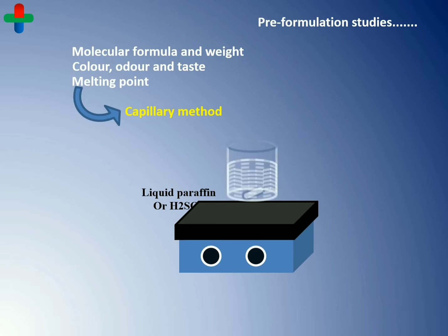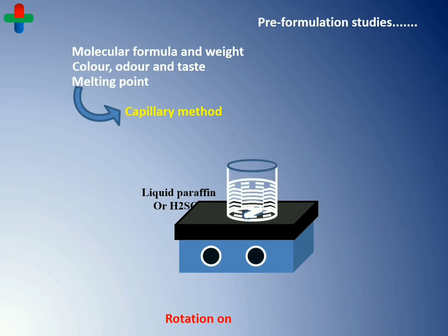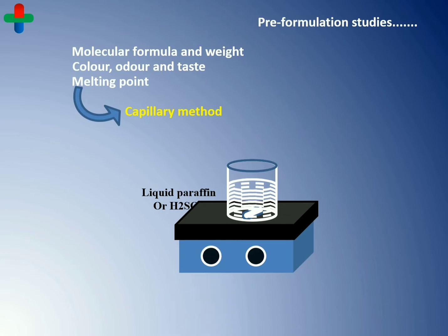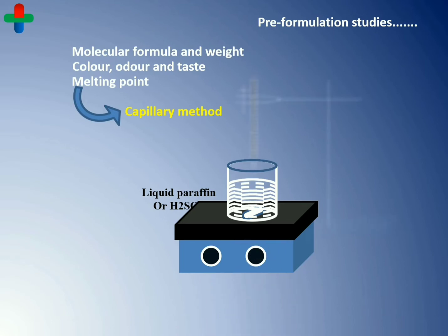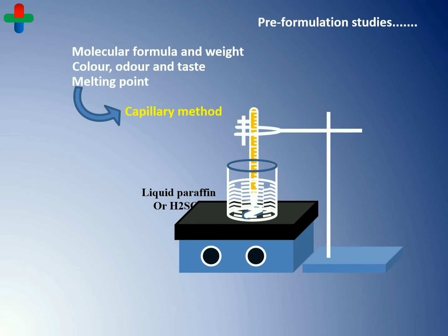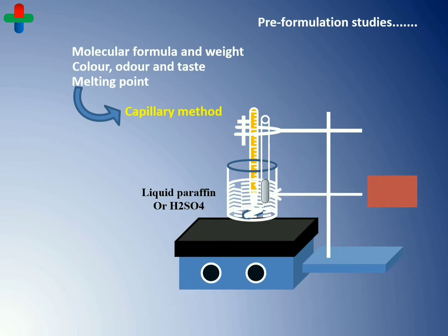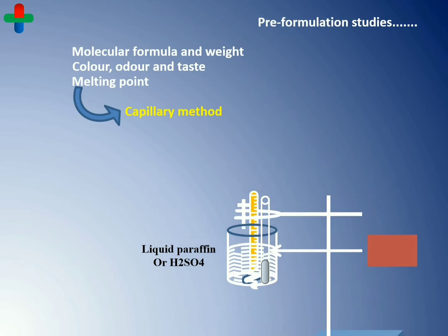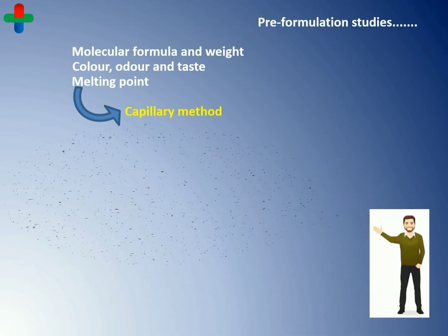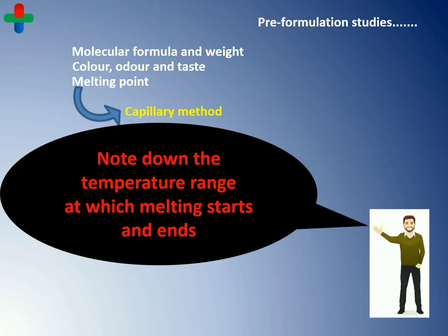One of these liquids can be taken in a beaker and kept on a heating plate. We can start heating and stirring the beaker contents slowly at 50 revolutions per minute. Further, we can fix a thermometer and a drug-loaded closed capillary into the maintained beaker. Now wait for the rise of temperature up to the melting point of the drug, and when the drug starts melting, note down the temperature range in which melting starts and ends.